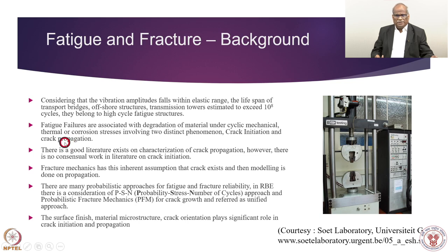As I mentioned, there is no literature on crack initiation, so we make an assumption, and then for crack propagation we work on modeling. Fracture mechanics has that inherent assumption that a crack initiates, and propagation is the detailed modeling, and then there are many probabilistic techniques. One technique is called PSN, probability, stress, and number of cycles, the PSN curve approach. The second is the probabilistic fracture mechanics approach for crack growth, referred to as the unified approach. And then there are the surface finish and material.